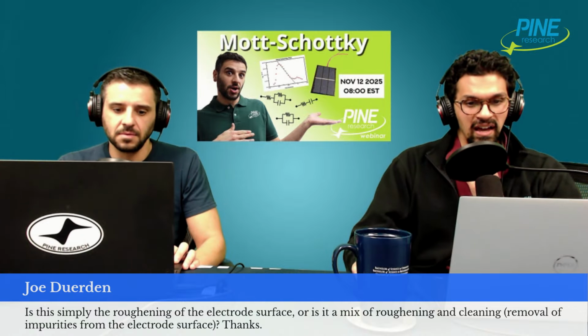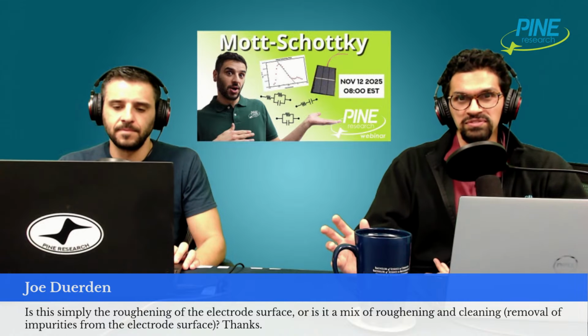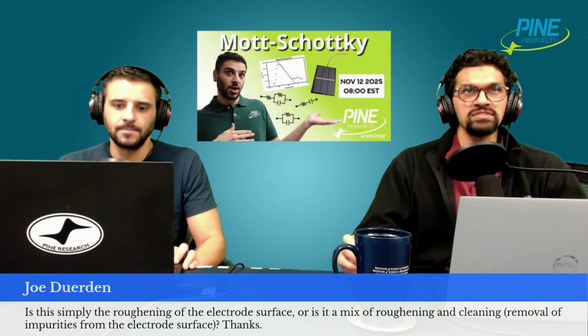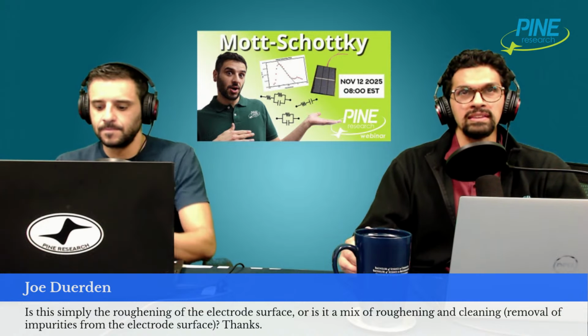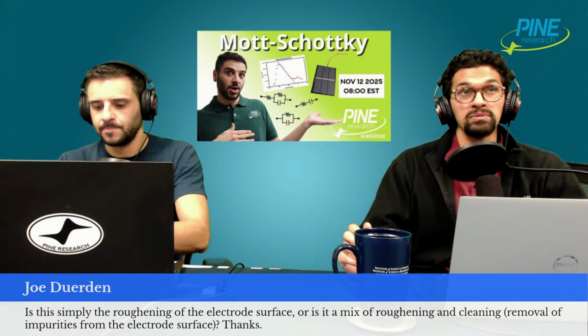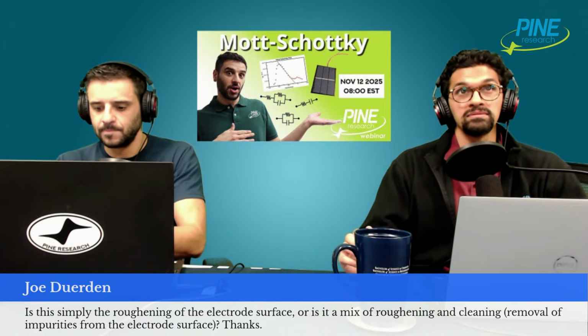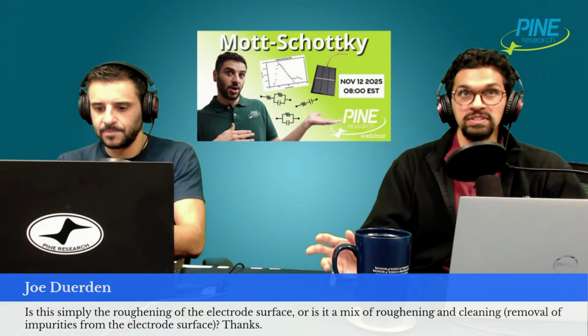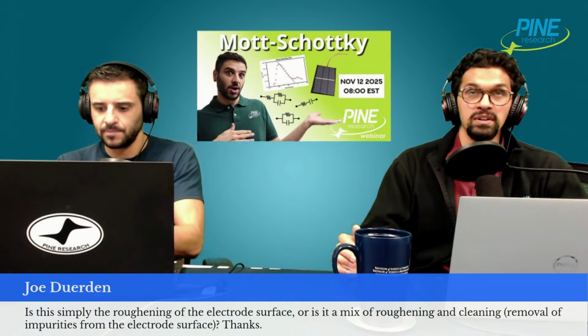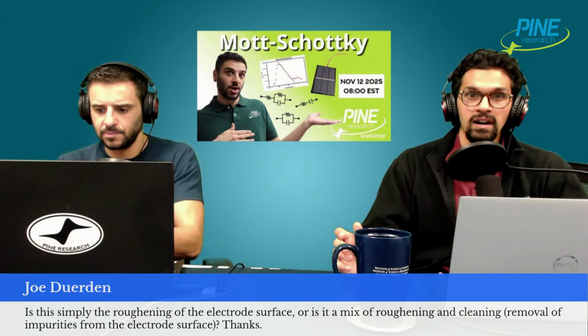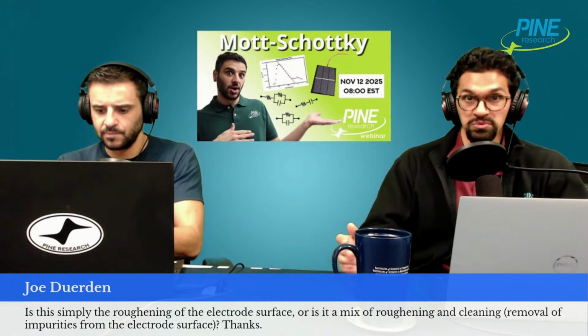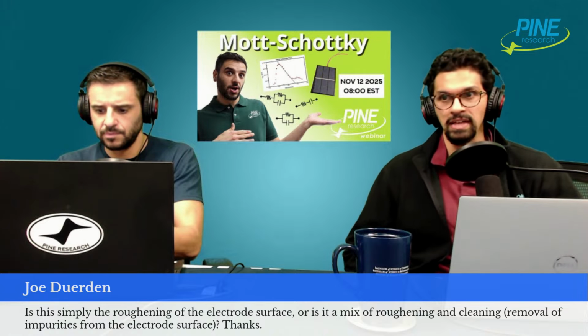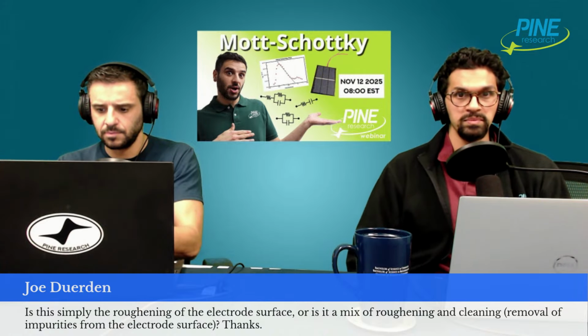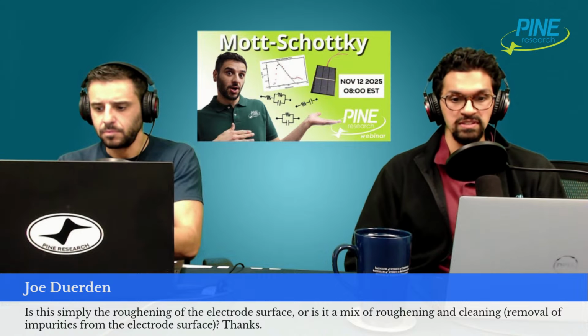But yeah, I've always been taught that it's a cleaning technique. But of course, I can understand there being some surface roughening, and that would, in my opinion, only be due to the formation of the platinum oxide. You're forming a platinum oxide, you're removing the oxide, you do that multiple times, and so there is some roughening. So you see oxidation current in the platinum, and then you see its reduction. There's a huge platinum reduction peak, and then you see the hydride formation on the different crystal faces.